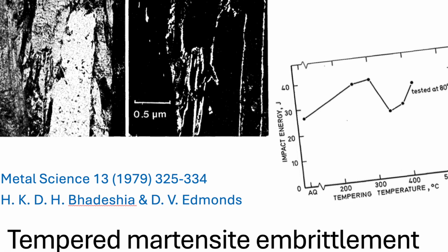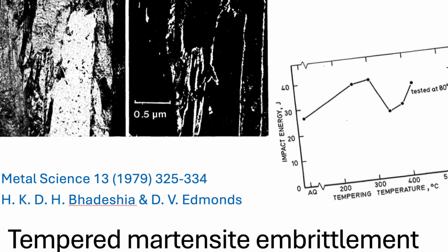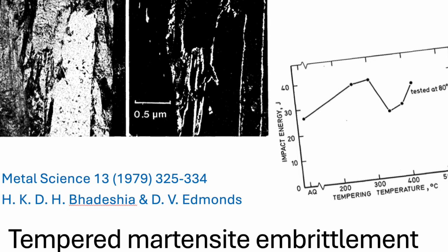Exactly. It's a huge signal that the mechanism causing that minimum toughness is highly localized, it's extremely temperature dependent, and it must be chemically distinct from the general processes that govern the overall softening. So TME isn't just general fatigue or wear. Not at all. It's a specific structural failure triggered by a very particular narrow phase transformation event happening inside. We have to go back and look at those laths again.